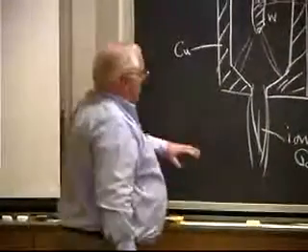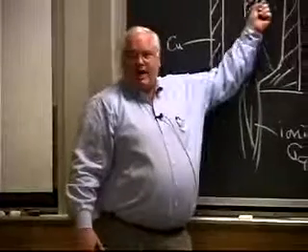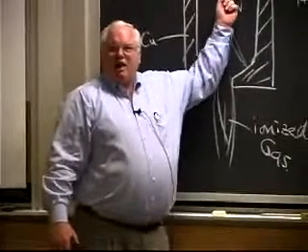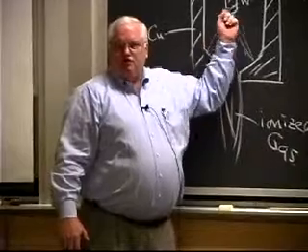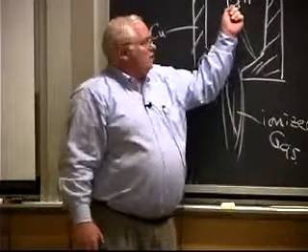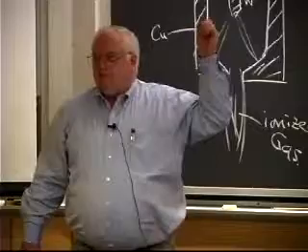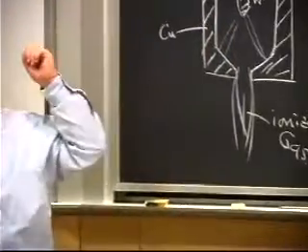The reason they use hafnium is they find they can use air as the gas through here, whereas if you use tungsten, anybody know what would happen if you struck an arc with a tungsten arc in air? Tungsten actually forms an oxide, tungsten trioxide, WO3, which is volatile at about 1500 centigrade. And the tip of that electrode is like 2500, 2800 degrees centigrade. And so you would get a white smoke, which would be tungsten oxide, and your electrode is just burning away, which is not what you want.